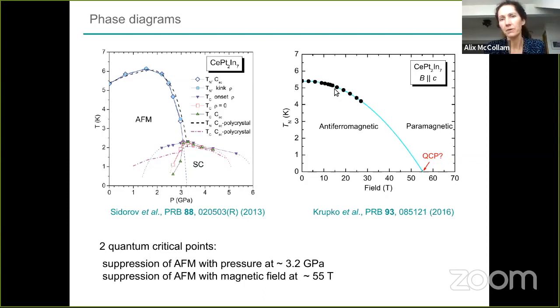These are measurements from heat capacity, which is from this article here. It is quite difficult to do heat capacity in the pulsed magnetic field. So we've been trying to find a way to extend this phase diagram, but it's very difficult actually to identify this antiferromagnetic transition. In specific heat, we see a very sharp feature for the antiferromagnetic transition here, and it becomes less distinct as we go along. We have now done measurements up to 35 Tesla, but this just extends our phase diagram to here.